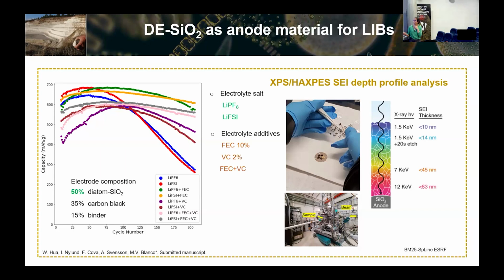So we did some XPS at the lab and some HAXPES at the Spline beamline of ESRF to try to see what this SEI layer was made of, what is the chemical composition and the structure layer by layer. So we use soft energy from a lab source, and we did some etching to try to scratch down a bit and see what was underneath. And then we used 2 high energies, 7 keV and 12 keV, to try to go deep inside of the SEI.